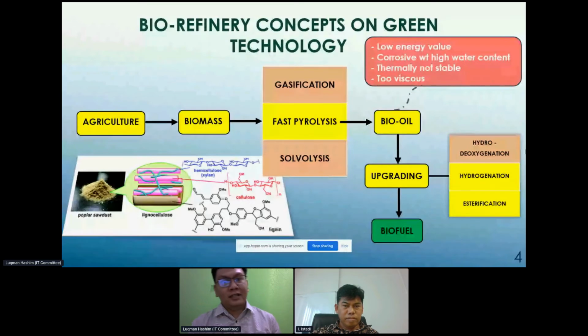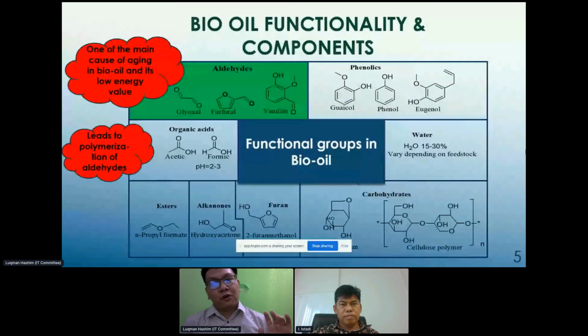Speaking of bio oil, those problems I mentioned before, one of its main contributors, and the one that we are focusing on today, is actually the aldehyde furfural. Furfural is the main cause of aging for bio oil, hence why we are focusing on this particular bad guy. And it has relatively low energy value due to its structure, but we can do something about it. Furthermore, it shortens the shelf life of the bio oil by being very susceptible to polymerization, especially in the presence of acetic acid or any organic acid for that matter, which are abundant in bio oil.